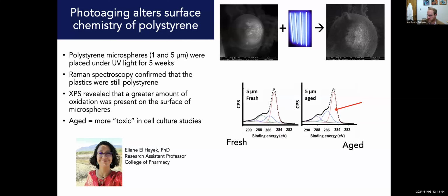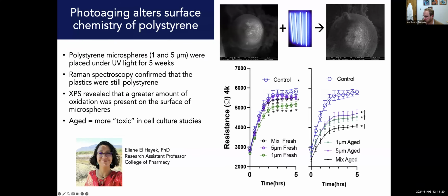We were able to show that, yes, in fact, this arrow is pointing to this little blue hump, which is the increased number of carbonyl formations on the surface. That's indicating that there is an oxidative change. There was a visual change, some roughening of the surface. So we definitely had something happening.